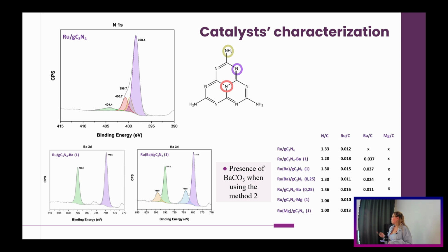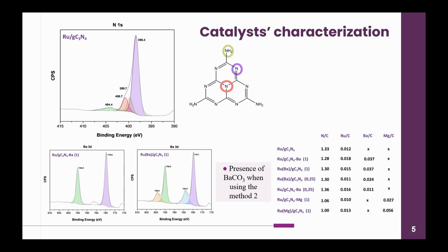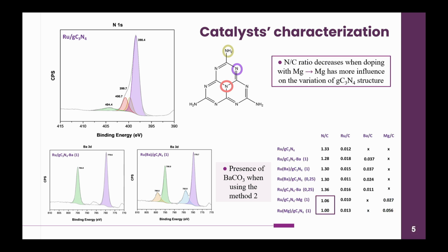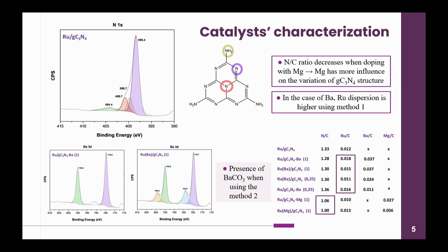Also, with the ratios obtained from XPS, it's interesting that the nitrogen-carbon ratio significantly decreases when doping with magnesium, and that may be due to the magnesium having more influence on the C3N4 structure variation. And when doping with barium, the ruthenium dispersion is higher when doping using the first doping method, which was mixing the alkali and the urea before the thermal polymerization.